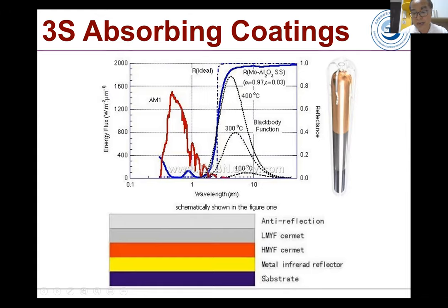It's also designed with multilayers, by some physical method, by vacuum coating, by vacuum sputtering. And so you see here is a glass substrate, and this is actually a solar heater working principle, and we have been working on it, using the substrate and making multilayers: infrared reflectors with high metal content and low metal content, and anti-reflective layers. So this is the optical design.